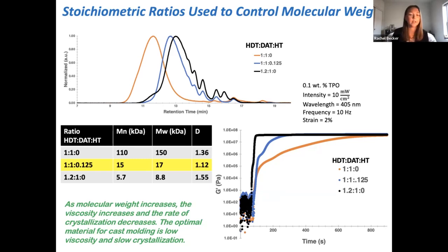And if the crystallization rate is too fast, it's not going to work for 3D printing because the layers need a gelation period in between the polymerization and crystallization in order to stick to each other and create an accurate print. So we wanted to focus in more on the two ratios that have sort of a gap between the quick polymerization and the crystallization process. So we found that the 1:1:0.125 ratio gave us sort of the best of both worlds with that low molecular weight, as well as a little hump in between polymerization and crystallization.